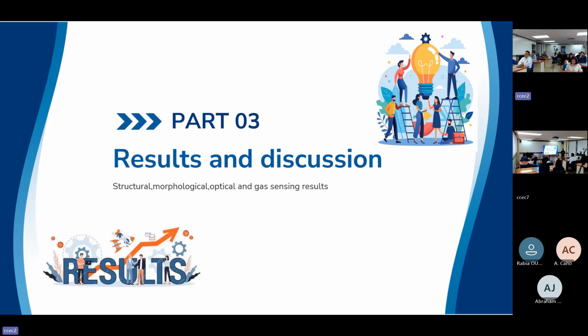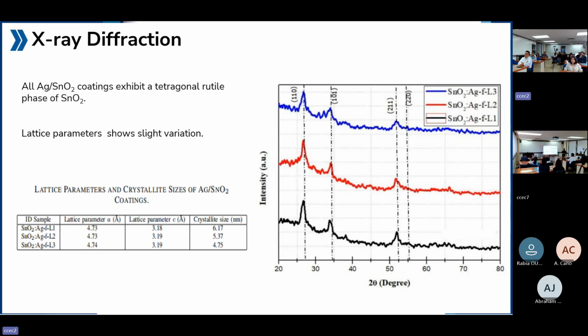Part 3 is results and discussion. Starting with the results and discussion, let me begin with structural analysis. The structural analysis was done with XRD, where all the X-ray diffraction patterns of Ag-added tin oxide showed and confirmed the tetragonal rutile phase of tin oxide. Interestingly, there was no secondary phase of Ag formed, which confirms the successful addition of Ag into the tin oxide matrix.